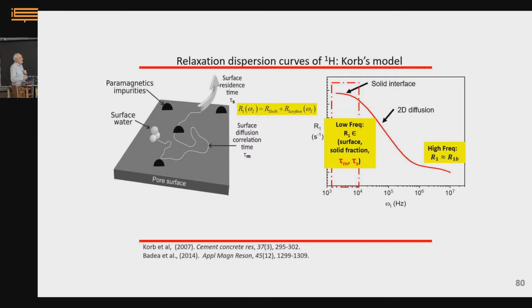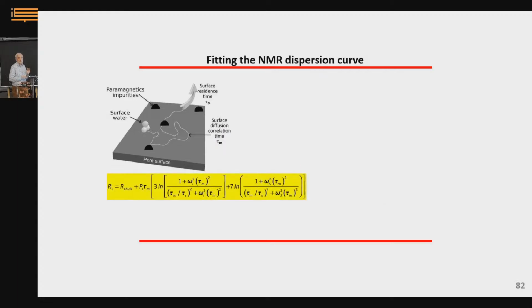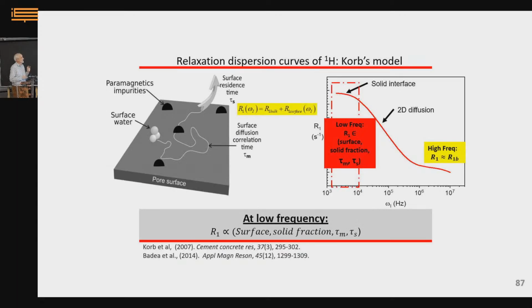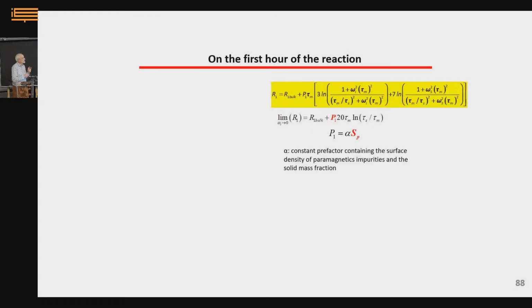But if you go at very high frequency, you're probing very short time. So the molecule of water doesn't have time to adsorb on the surface, and you just have the relaxation of water in the bulk. At very small frequency, you're probing long time. So the molecule has time to come to the surface, and it has time to probe the whole surface before it desorbs. It's a little more complicated than that, but roughly speaking, that's what it is. So at low frequency, asymptotically going to zero frequency, you recover the surface area of the system. That's what I have written here, the full expression. But the asymptote here at zero frequency is, of course, frequency independent.